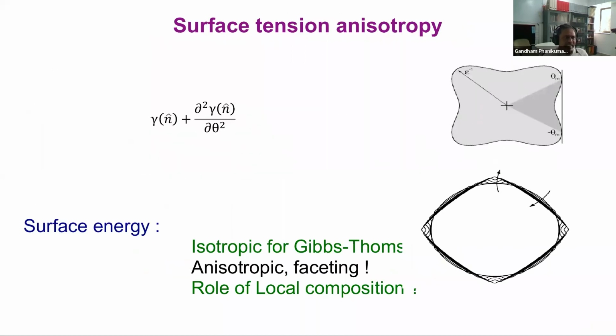Now, the driving force is then combined with the surface energy, which is anisotropic, and together they lead to various pattern formations such as these facets. Facet means sharp faces. Sharp faces are bad news. They are not desirable. And what kind of phases will have sharp faces? For example, the intermetallic compounds, particularly the detrimental ones, usually have sharp facets, and we don't want them because they are detrimental. A sharp face also means that a crack can move between the intermetallic compound and the matrix a bit fast, and therefore they are actually a double whammy.